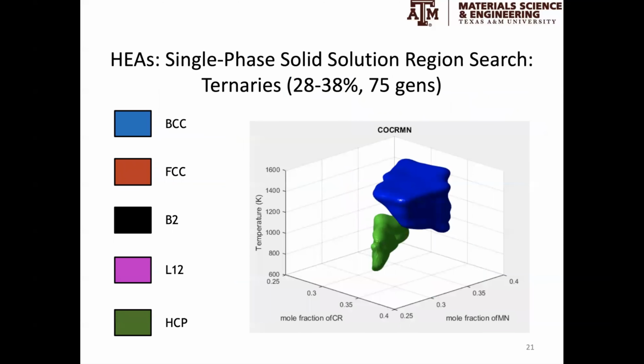This is what happens when we say, for example, that we want to identify the single phase solid solution regions in a ternary medium entropy system. Just by running our alloy search scheme, we immediately find that there are isolated regions—one corresponds to hexagonal close packed structure and the other corresponds to BCC—that solve this problem of finding a single phase solid solution in this three component system.